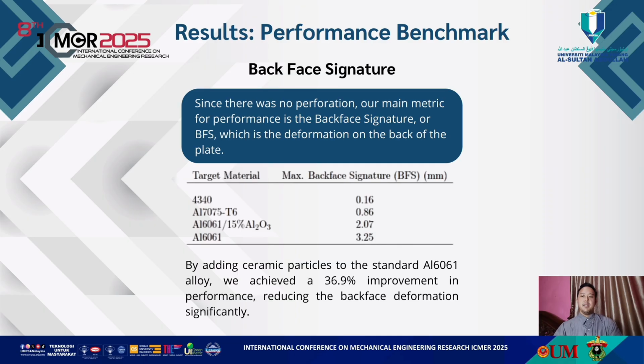As you can see from the table below, 4340 steel is the top performer with a very small BFS of only 0.16 mm. Among the lightweight options, aluminum 7075 T6 performs very well with a BFS of only 0.86 mm. The aluminum 6061 composite comes next with a BFS of 2.07 mm. For comparison, the standard aluminum 6061 base alloy had the largest deformation at 3.25 mm. By adding ceramic particles to the standard aluminum 6061 alloy, we achieved a 36.9% improvement in performance, reducing the back face deformation significantly.